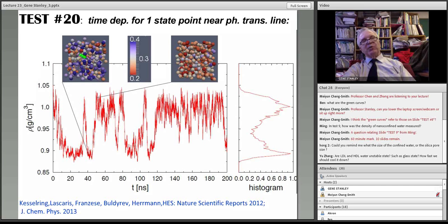Furthermore, if you know anything about phase transitions, you know one of the most striking things is a system is not uniformly low density and uniformly high density. That's not the case. If that were the case, all these balls would be red, unstructured, and all these balls would be blue, structured. But instead, there's a huge heterogeneity. In fact, a measure of the size of the heterogeneity is the correlation length, which is only on the order of a few water molecules. So let's now do the last thing.